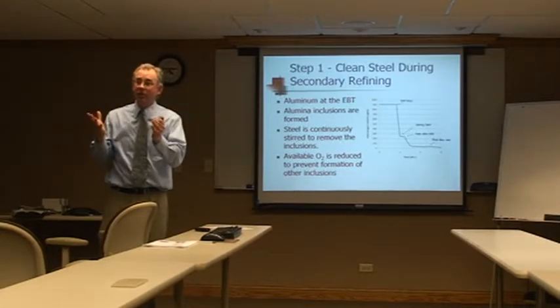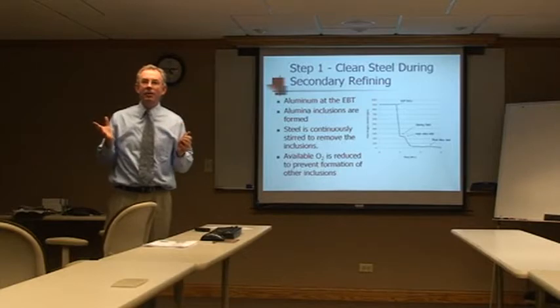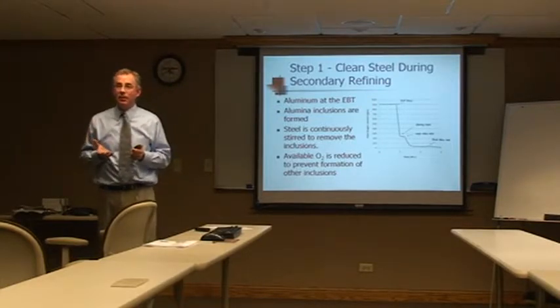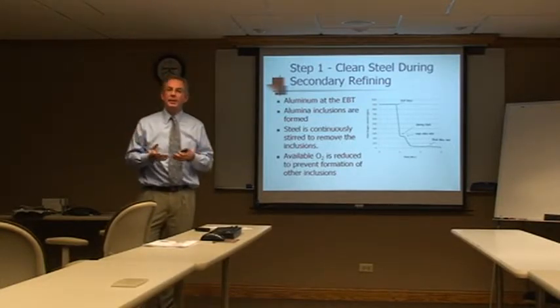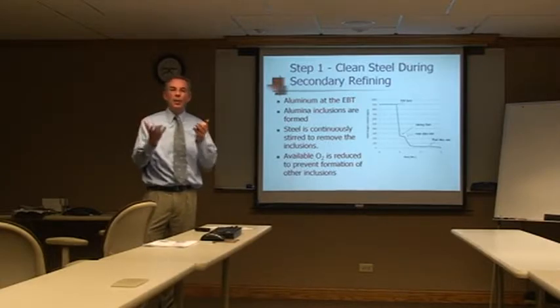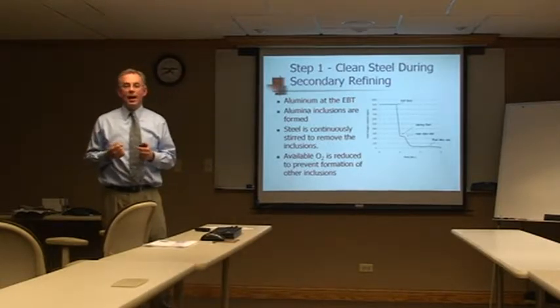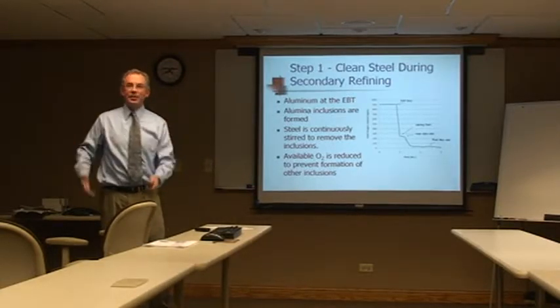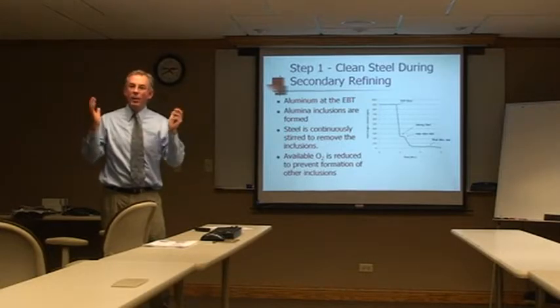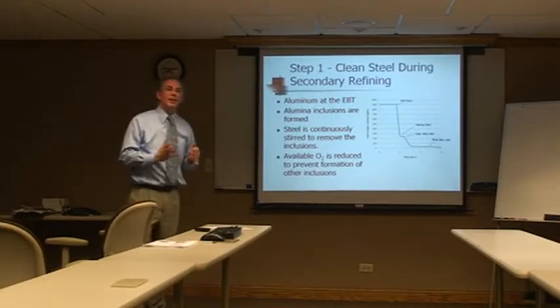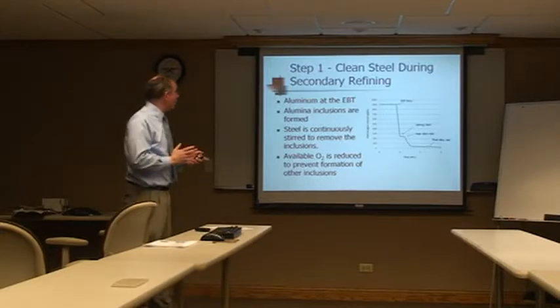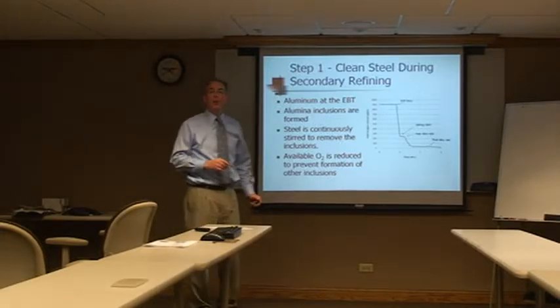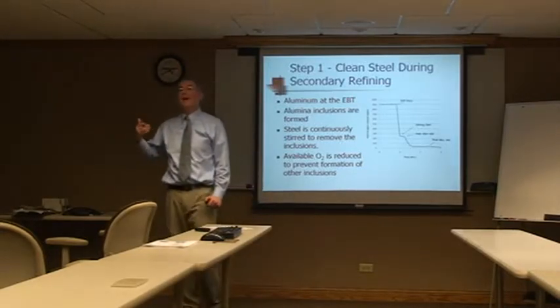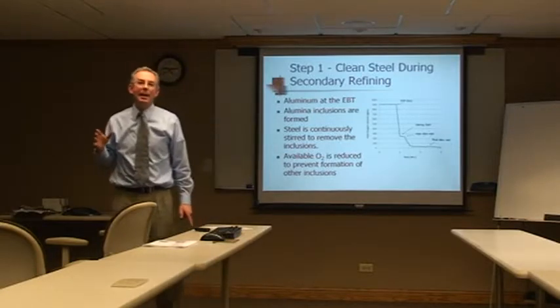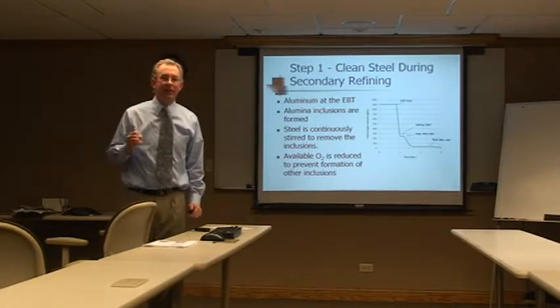We have all this oxygen, which if we don't take care of this oxygen, we're going to end up with a very dirty steel. Oxygen is going to be free to react with any element that wants to tie up with oxygen, be it silicon, whatever. We want to make sure we take care of it and we control it. And how we can control it is using aluminum. By and large, 95+% of the grades of steel that we make at EQS are aluminum killed.